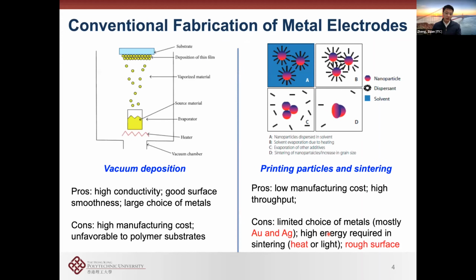But if you look into how metal electrodes are made conventionally in the semiconductor industry or the new printed electronics industry, they're basically made in two ways. One is vacuum deposition, for example, thermal evaporation, electron beam evaporation, or sputtering. In another way, you use nanoparticle inks or microparticle inks, formulate them so that you can print them on top, and then sinter them by heating or by localized melting or laser melting. Then you can merge the particles together and form the so-called metal electrodes. That has been done in the last 20, 30, or 50 years in industry and also in academia.